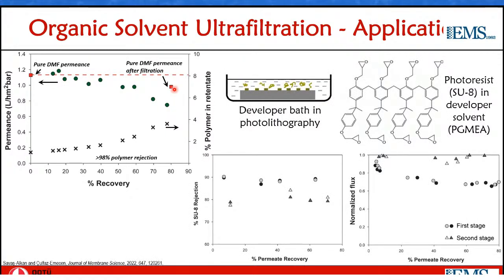The second potential application we thought of was one from the electronic industry, from a photolithography process. Here we worked on removing a photoresist, an oligomer SU8, as you see here, from what's called the developer solvent, PGMEA. This kind of a waste stream appears in the developer bath in photolithography, where the photoresist on the substrate is cross-linked in a pattern through a mask, and then the non-cross-linked region is dissolved in the developer solvent to reveal the pattern. And then you end up with a waste containing uncross-linked resist inside this developer solvent.